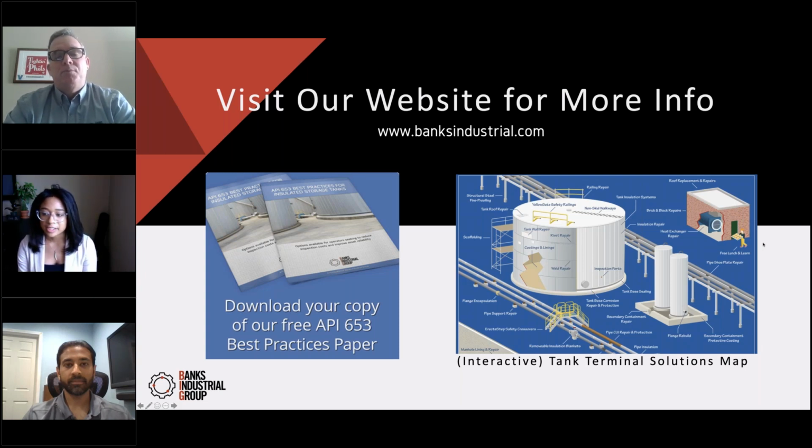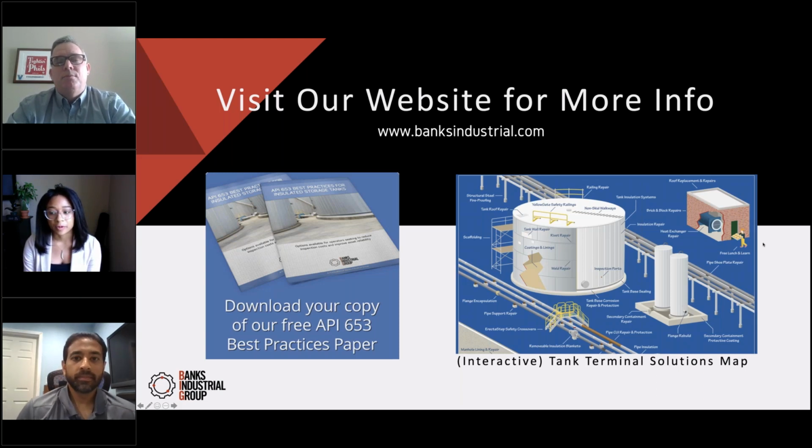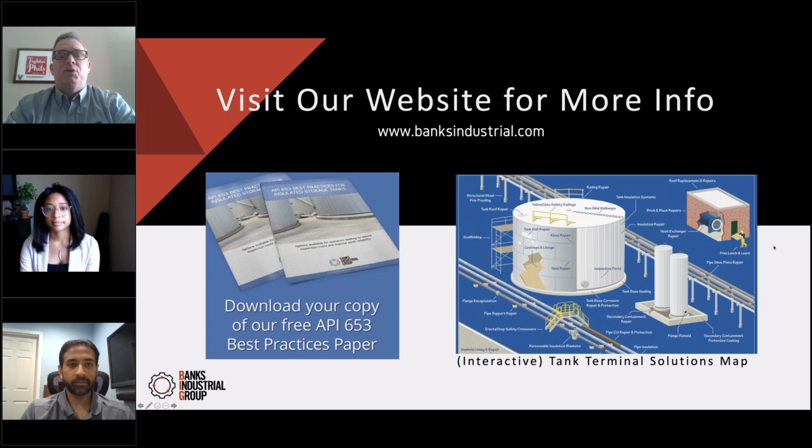Thank you. Really good question about Belzona repairs. When making the Belzona repair on the tank roof, if you can't grind or create spark, what's best practices for surface preparation? We'll just do a hand surface preparation, just using sandpaper or some sort of rough material to try and get a profile so that Belzona can attach to that roof. So if there's any kind of corrosion up there, we'll try and get rid of that using just hand tools. Not using any kind of grinding equipment or sandblasting, for instance. But ultimately, you've got to be able to get a good profile so that Belzona can stick to that clip, and it could also stick to the roof of the tank.